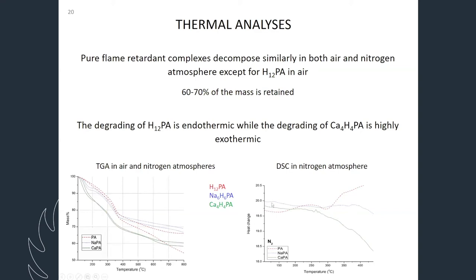We also did DSC, differential scanning calorimetry. There we can see this green one is the calcium salt. They are actually exothermic, so they are giving heat, while the pure phytic acid is endothermic. And these experiments were done in nitrogen atmosphere. The data I showed, we'll try to interpret later when we get our results.